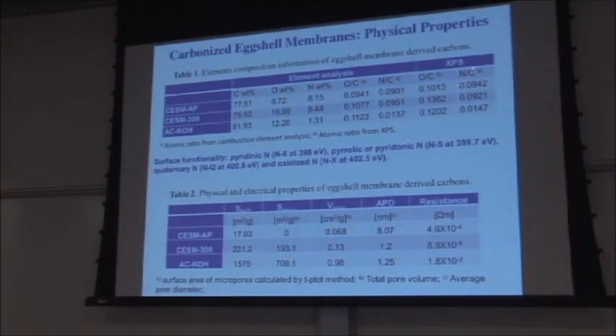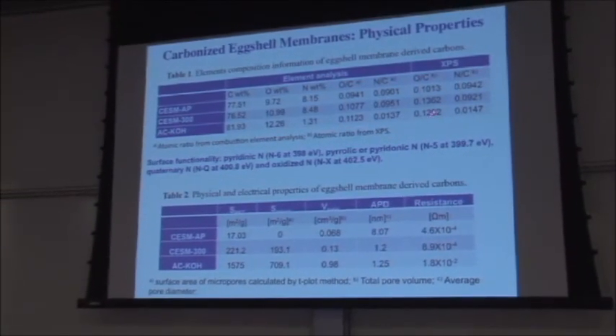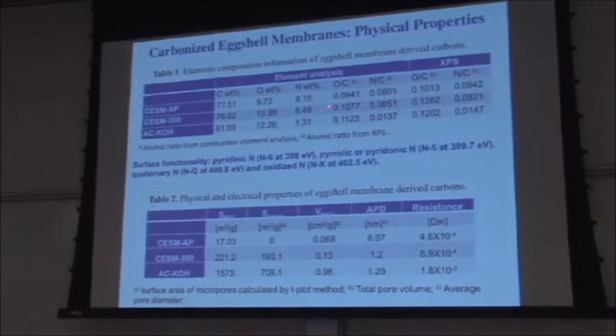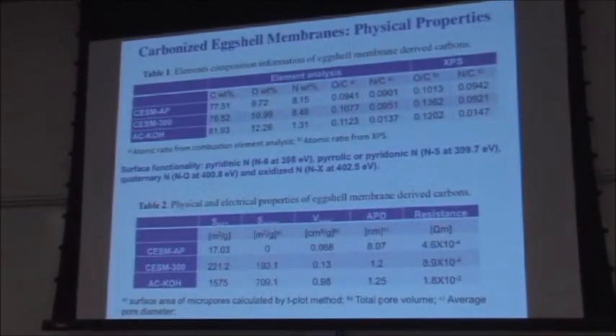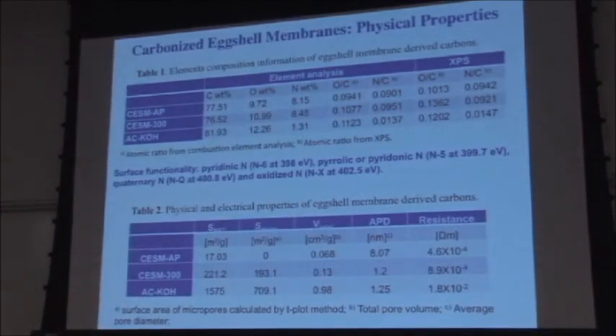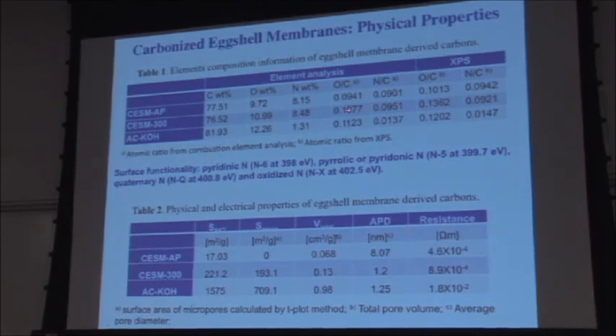So this is the neat part. We're able to achieve, both in the as prepared and in the material activated at 300 degrees C, very high nitrogen content. So this is from elemental analysis. This is from XPS. And if you compare the two, you'll see that after the activation, your surface nitrogen content is a little bit lower on the surface than in the bulk, though not that much. And your oxygen is higher on the surface than in the bulk, as you would expect.